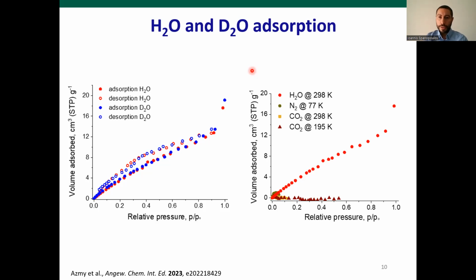Considering the much smaller kinetic diameter of water compared to nitrogen and carbon dioxide, these studies are in perfect agreement with the adsorption of water and deuterium oxide in the cryptand ligands. We've also found that based on the maximum water uptake, this uptake corresponds to 1 water molecule per cryptand ligand, which was further verified by the DFT calculations.